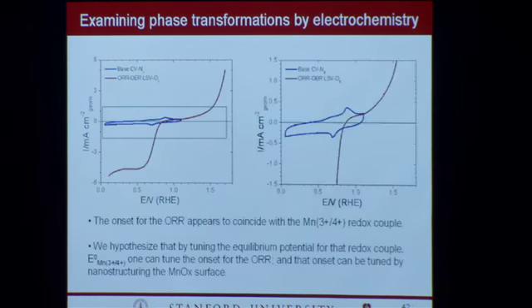And what we hypothesize, just taking a look at this CV for the aficionados out there, we're looking at onset of ORR, onset of oxygen evolution. We see that there is a phase transformation, Mn3+ to 4+, right at that potential where oxygen reduction occurs. And so we hypothesize by changing our material, by changing the nanostructure of our material, we can actually change this equilibrium potential for the change in Mn2O3 to MnO2, which will then allow us to tune this onset potential to the right, which is where we want it to be, to make for a better fuel cell catalyst.